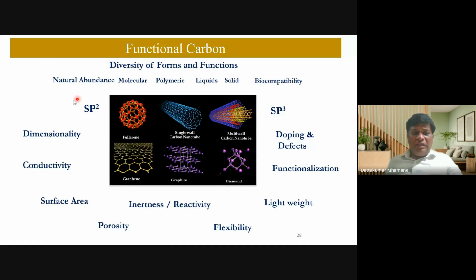So many properties are present in carbon. That is why carbon is called a functional material. Carbon is sp2 hybridized, carbon is sp3 hybridized, dimensionality is there, conductivity varies amongst the allotropes of carbon, surface area varies. In the case of single layer graphene it is 2600 square meters per gram, but in the case of graphite it is like 50 or 60 square meters per gram. Then conductivity is very high. Graphite's conductivity is also high, graphene is also high, but single layer graphene is again higher.